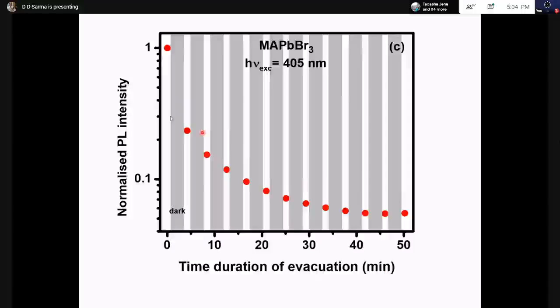I can do that by doing an experiment intermittently, where I switch on the light, do an experiment, put it into the dark, don't do the experiment, again switch on the light, do the experiment, and keep alternating. And here also I find exactly the same trend, and whether it is dark or light, it follows exactly the same smooth curve, suggesting that switching off the light is not helping me at all, which means what is putting it down is this continuous evacuation time that the system is feeling.